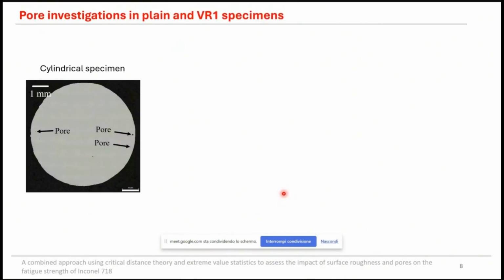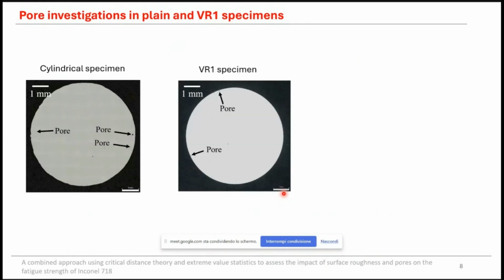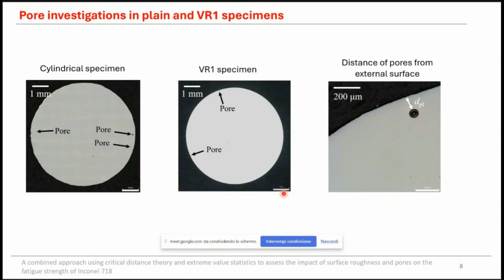Given the key role of pores, we investigated 2D images obtained through the optical microscope, trying to identify two key variables of the pores: the pore diameters and distance from the external surface.